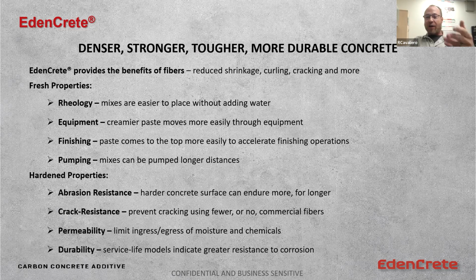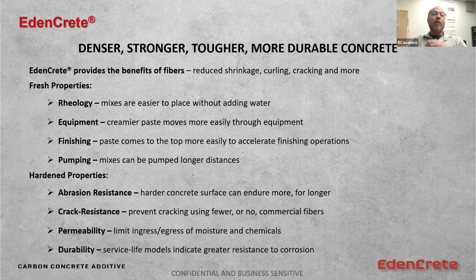So there's a benefit. Shotcrete, it helps with the ability of it to adhere, that lowers the dust, it makes it rebound less, and it makes it lower the hydraulic pump pressure through the equipment. So equipment can run with less wear and tear, and they can pump more for a given gallon of gas, right? This is all sustainability. EdenCrete was created because of the strength, the toughness, the hardness of the carbon nanotubes. The bottom set of bullets is what EdenCrete was created for, right?